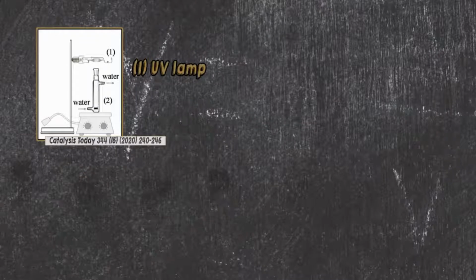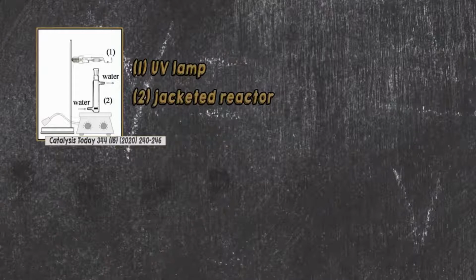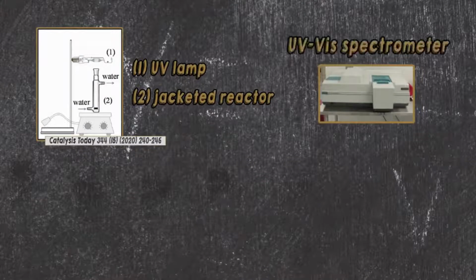In this figure, you can see the reactor we used to evaluate the indigo carmine dye discoloration. You can also see here that we used the UV lamp to simulate UV radiation to activate the photocatalyst. Also, we used the jacketed reactor to maintain room temperature. Each liquid sample we took was analyzed in a UV spectrometer to observe the indigo carmine discoloration. Now, let's jump into our results.